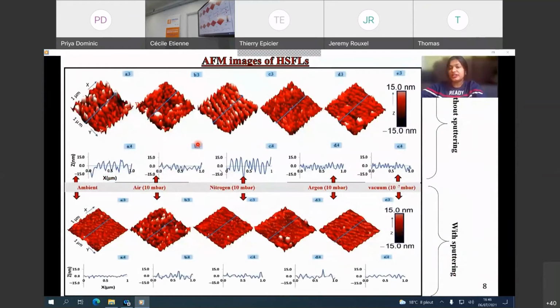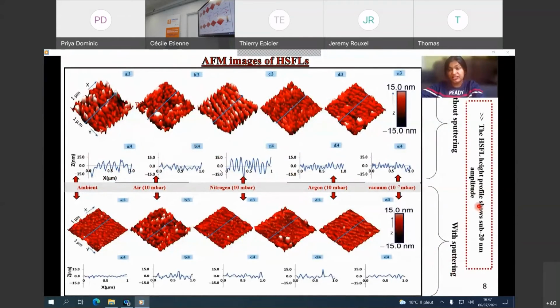And in order to get an idea about the height or the amplitude of the HSFLs, we did some atomic force microscopy imaging, and the height profiles corresponding to different gaseous conditions, without sputtering and with sputtering, indicate HSFLs of very small amplitude. So we have sub 20 nanometer amplitude of HSFLs formed for different gaseous conditions: for ambient, for air 10 millibar, for nitrogen 10 millibar, for argon 10 millibar, and for vacuum. And in order to verify the height profile that we got from AFM, we did some cross-sectional imaging using